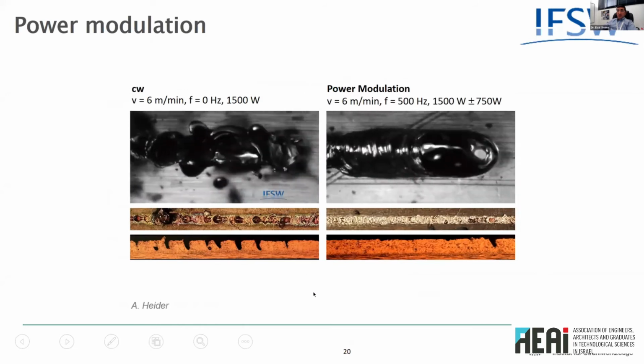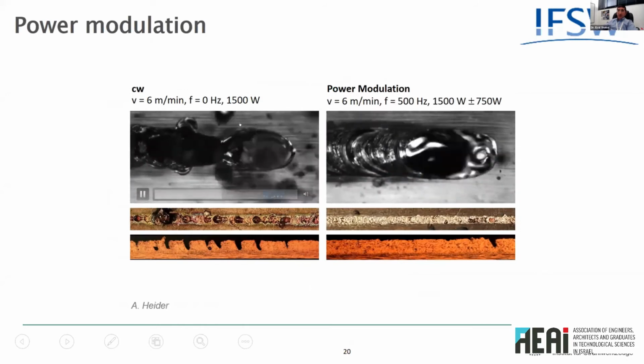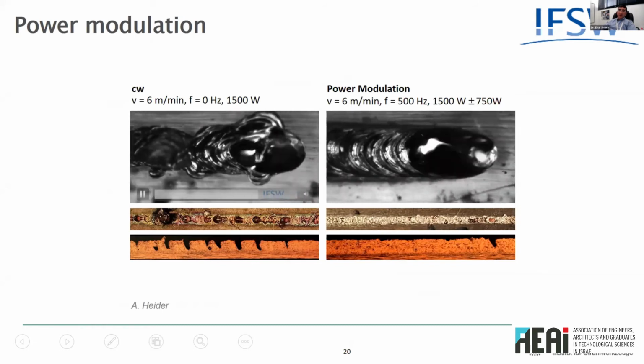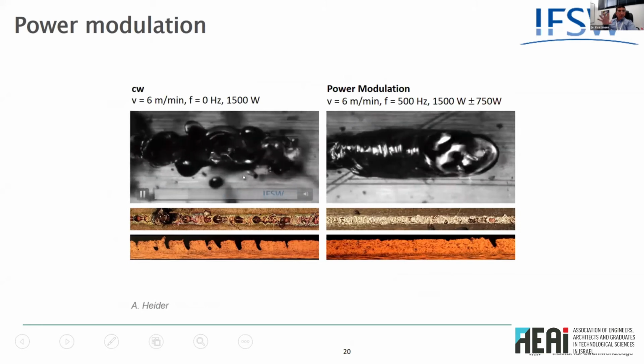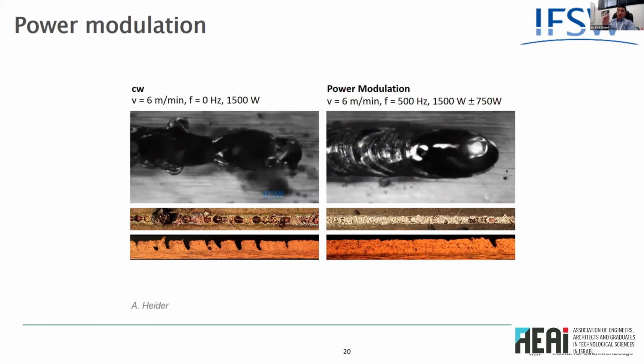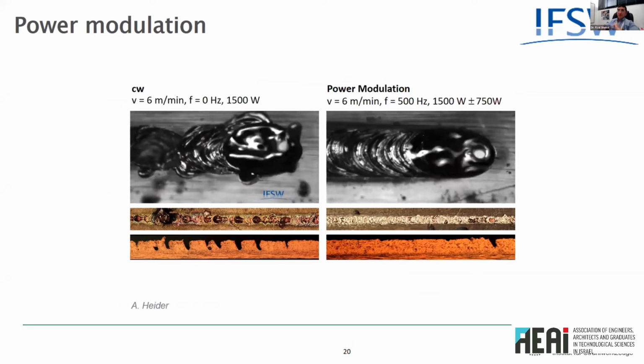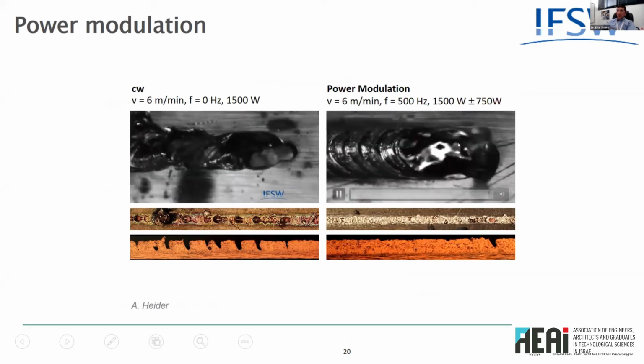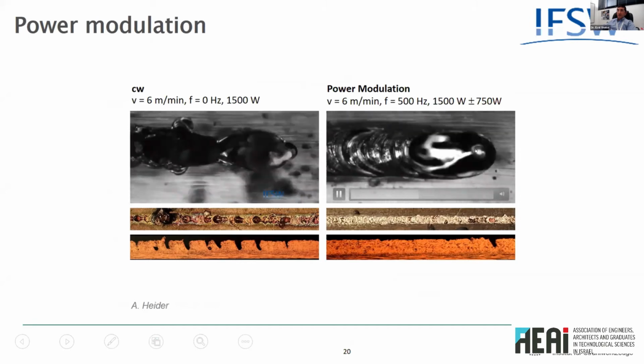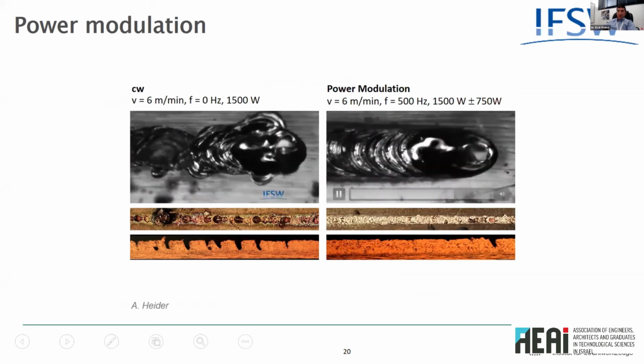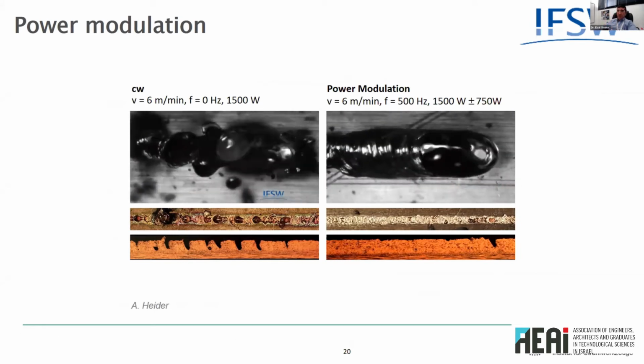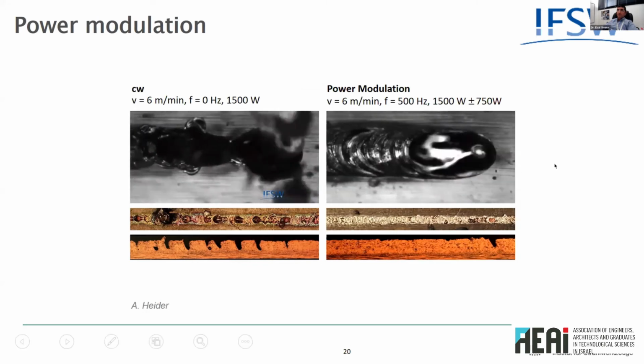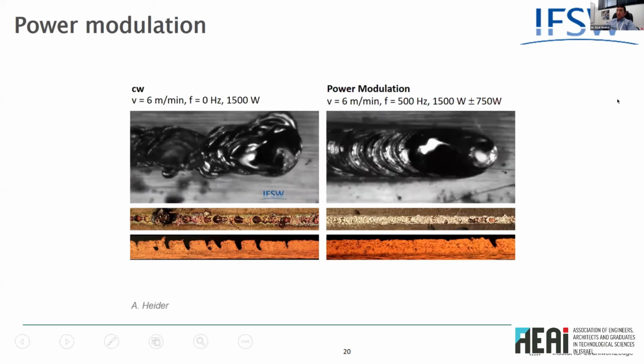Another example is welding of copper, and what you see here is a lot of sputter. This sputter occurs because you have a lot of power going into the material and you have these explosions. But if you can modulate the power, you can actually have a sputter-free weld. This is done by modulating the power, reducing it before you create sputter. This is the work done by University of Stuttgart, IFSW.